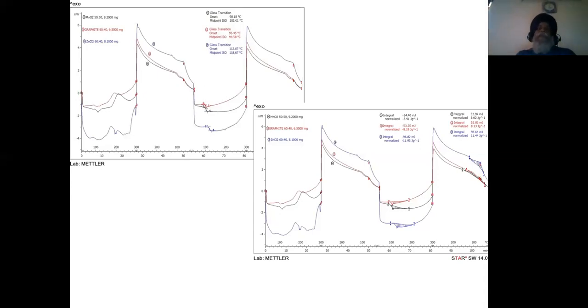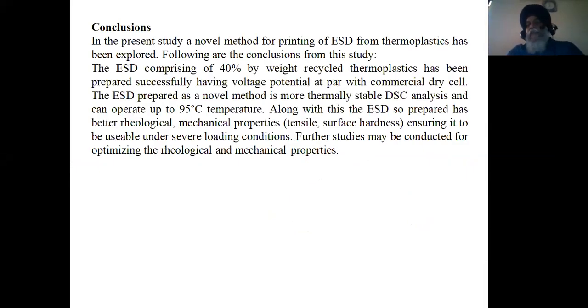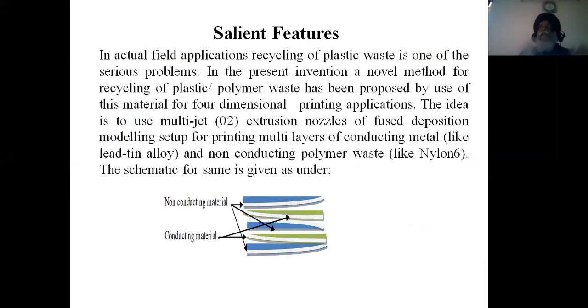Similarly, we did a similar study at sub-zero temperature, and what we observed, even at minus 25 degrees Celsius, this is giving me good voltage. Otherwise, our normal batteries are not workable at such low temperatures. So again, what is the advantage we are getting? One is we are consuming the plastic, and what we observed in this work, we are able to consume up to 40% of the thermoplastic material, and of course it was workable at very high temperatures.